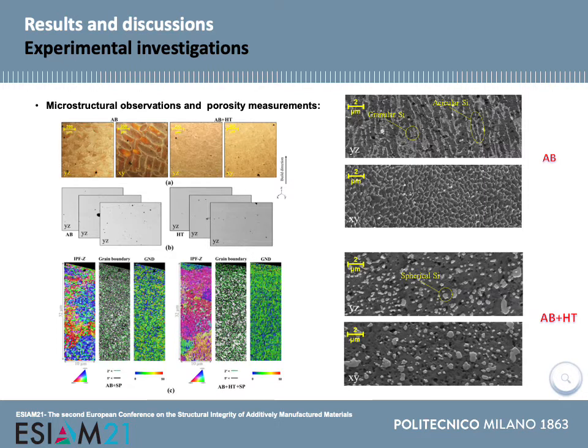In addition, porosity measurements were carried out using image analysis. Different cross sections in both as-built and heat-treated samples were used for backscattered SEM, and then the obtained images were binarized using imaging software, and then the fraction of black to white areas was considered as the porosity of the samples.